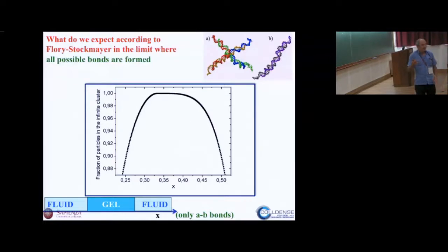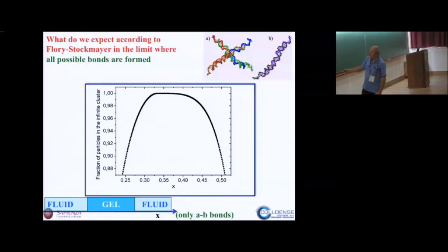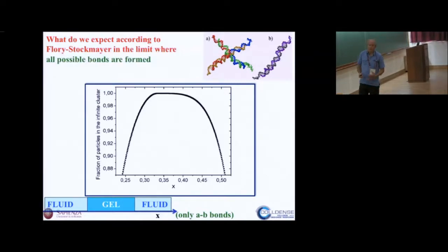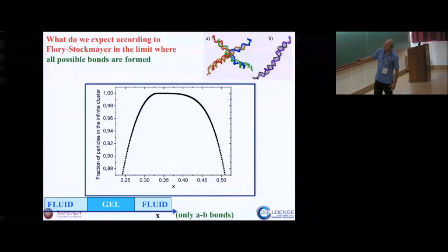Now, before doing it, let's decide what concentration we have to use. And again, the beauty here is that we can use the theory that we discussed 2 days ago, Flory-Stockmeyer. We calculated the cluster size distribution, the percolation probability, and all these quantities. And here I just show you, as a function of the relative concentration of the two particles, the number of particles which are in the infinite cluster. I just blew up this part here with very large infinite cluster.